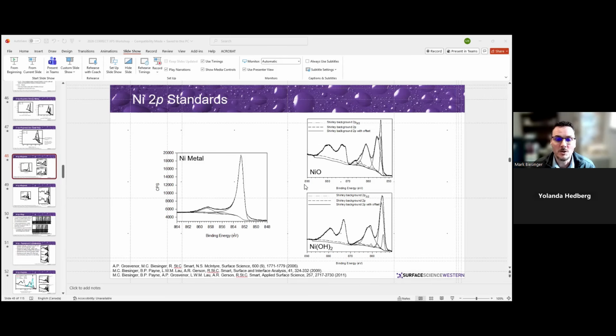They also ask, can you use a combination of Gaussian-Lorentzians to model that asymmetric peak shape? Yes, that will work. All you're doing is trying to get an area under the curve, and however you do that effectively works, but it has to be based on your standard spectra. If that works to get your area under the curve and you're happy with it, and it's giving you the right amount, then that certainly does work.